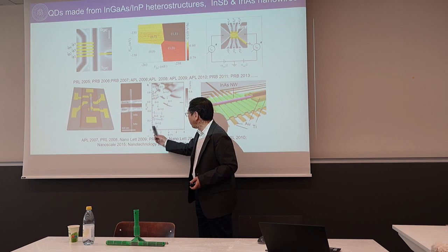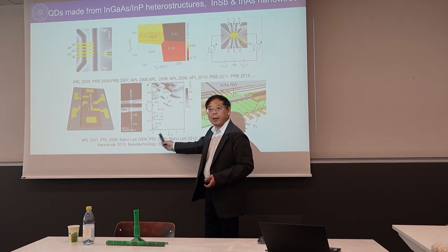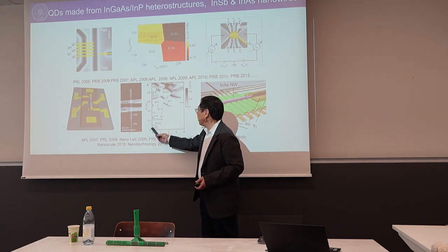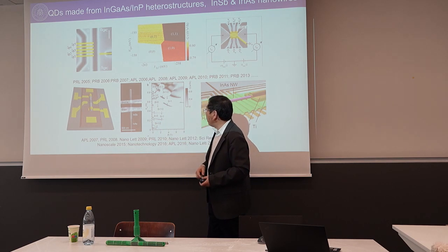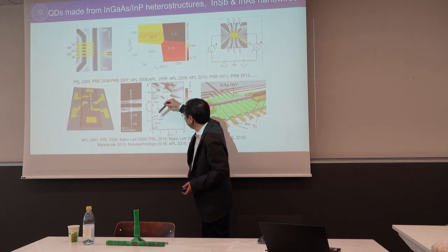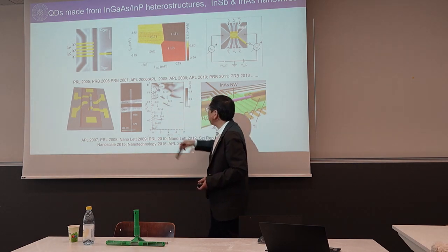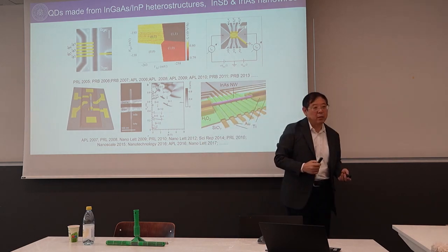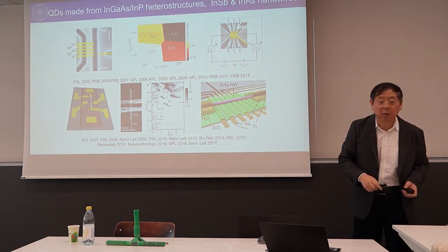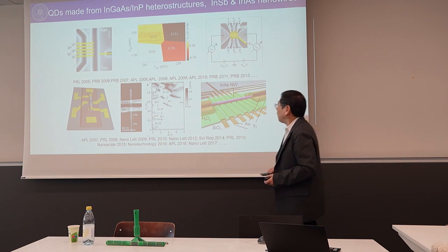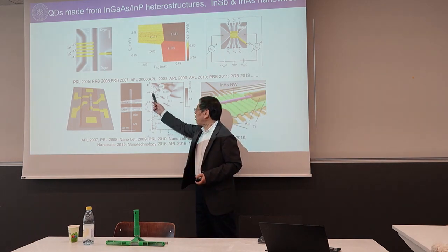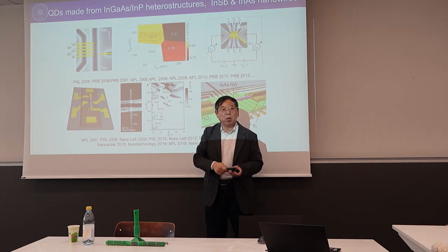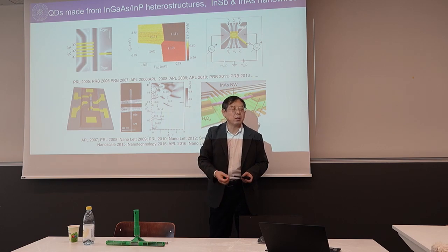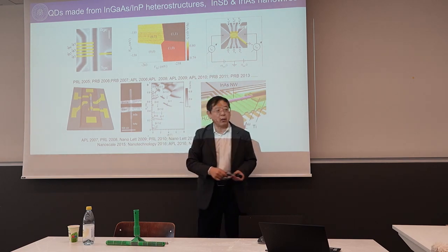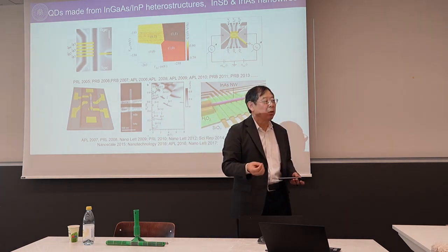So this is a different state. Magnified, they split. Then we see a lot of black stripes, and this black stripe is a Kondo effect. So I will not go into more detail. And the most important thing here is not the Kondo effect. We see so-called correlation-suppressed conductance. The Kondo effect is correlation-induced conductance.